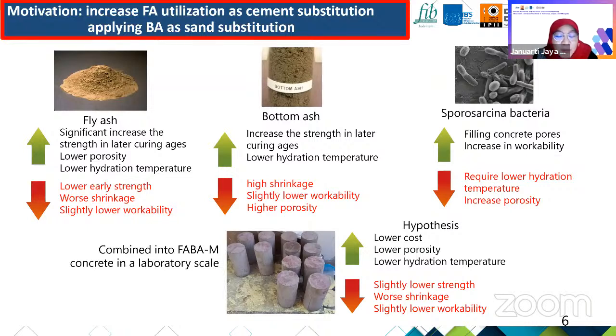So we use microbes in the mixture. In most of our experiments, we use Sporosarcina pasteurii as the bacteria especially for concrete. And then we use these microbes, and also it is found that the microbes created gas as the metabolism product during the casting. So it increased the workability of the concrete during casting.